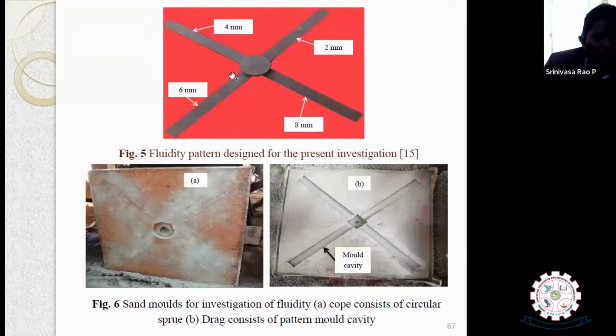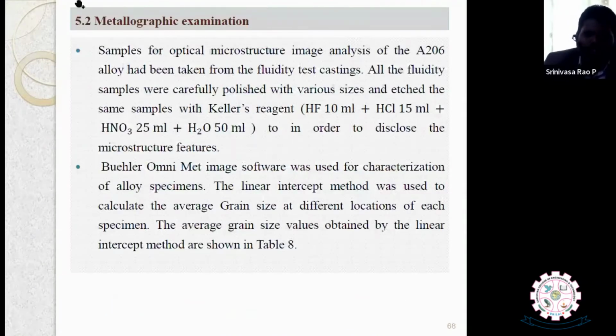See, 2 mm, 4 mm, 6 mm, and 8 mm are the thicknesses of the cross sections, because we mainly need to find out the fluidity of thin cross sections. So we have taken 4 cross sections of different thickness, and this is the mold we have made with the help of this pattern. And this is the mold cavity, and we used that optimized sand for the sand mold and made the castings.